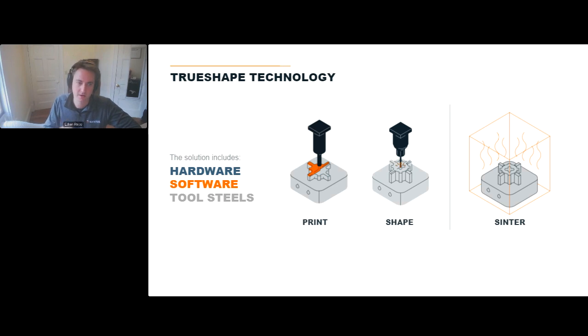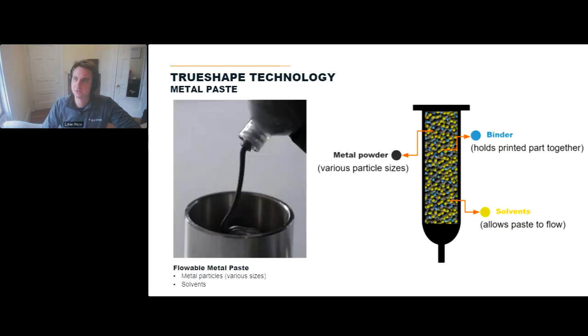And I'll walk through how this process works because it's very different than other metal 3D printing technologies and even other 3D printing technologies you may have seen. We actually print a metal paste. This paste is similar to a toothpaste that hopefully we were all using this morning. It's a flowable paste, it's viscous. And what that paste actually is, is a combination of metal powder, so metal particles, mixed with some binder like a glue, and then a solvent. We mix all of this together into a slurry, and this actually comes in a cartridge.